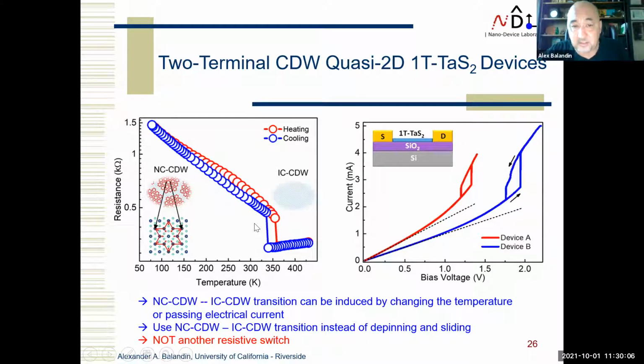It's a very robust transition. So now my idea is, can I use this hysteresis to get some device functionality from this quantum material at room temperature? And I'd also like to emphasize, we're not doing a regular resistive switch where what's important is the on-off ratio. Here, I'm just using the hysteresis window to get functionality. If you look now at the current of this typical device, we apply bias, and this is current. This hysteresis is the same one which you see on the picture on the left. And these are two different devices, different dimensions.